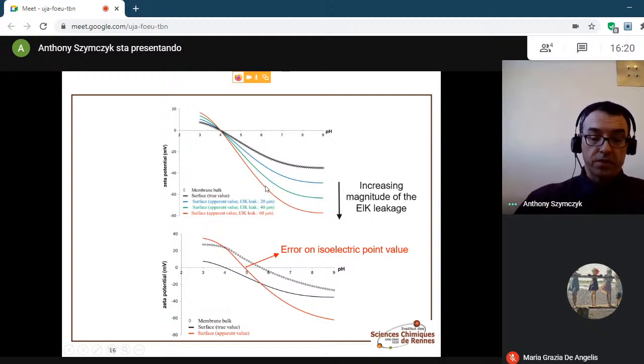The bottom figure shows that not taking into account the electrokinetic leakage phenomenon can also lead to errors in the determination of the isoelectric points of the membrane. This is the case if the isoelectric point of the surface layer is different from the isoelectric point of the membrane matrix, which can occur, for instance, with composite membranes.